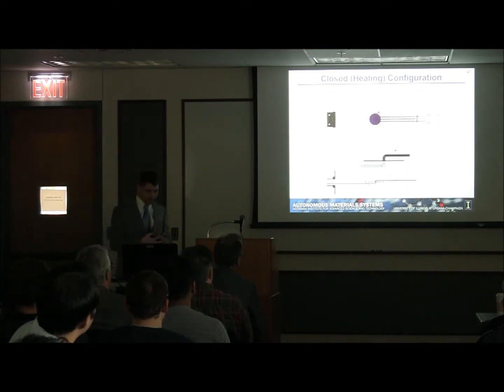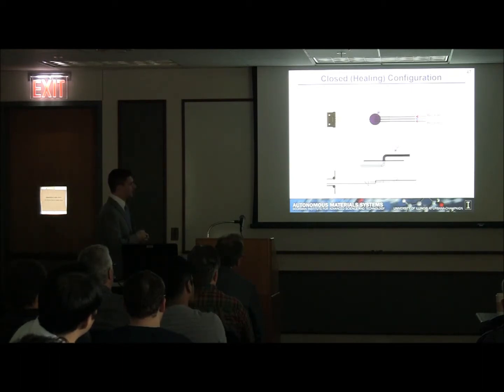So then we close the sample, and we have a delamination inside of the double cantilever beam, which is sort of representative of what we might have during impact. And we can deliver the healing agents to the backside through those channels in the backside, where we can have our resin and our hardener delivered to the crack plane, where they will then meet each other and mix and polymerize and heal the material.